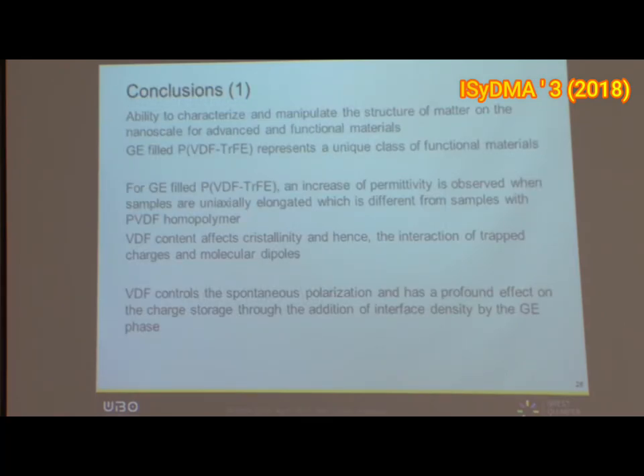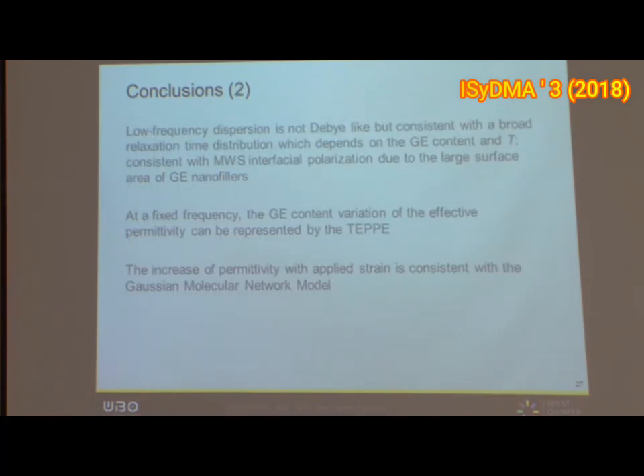So is it time for conclusion? What I would retain from this study is that the graphene filled electroactive polymer can be useful to simultaneously control the dielectric, the ferroelectric, and mechanical response, probably also the thermal response, but it's not a good sample for microwave applications.